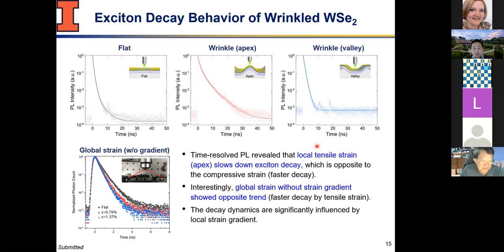And what you see here is that as different strain states are applied, we see different lifetimes. You can just see, without fitting or analyzing any further, that the apex, or the tensile strain, appears to give you the longest lifetime. Flat appears to be somewhere in the middle. Valley compression gives the shortest. But what's interesting, the point I'm trying to make, is that this was completely opposite to an experiment that people have done.